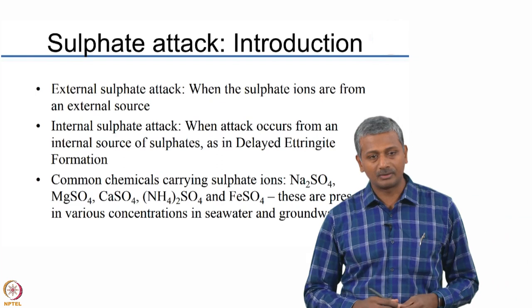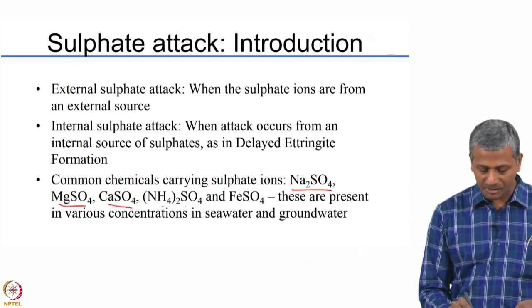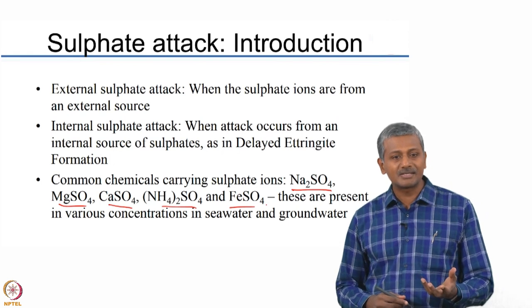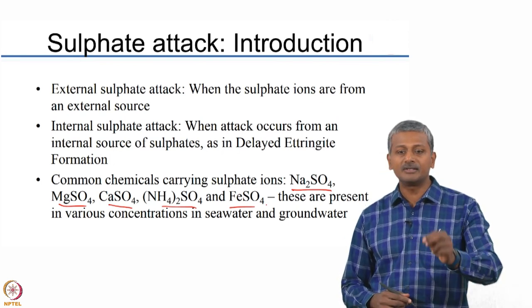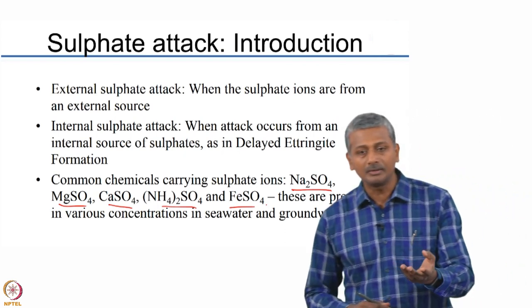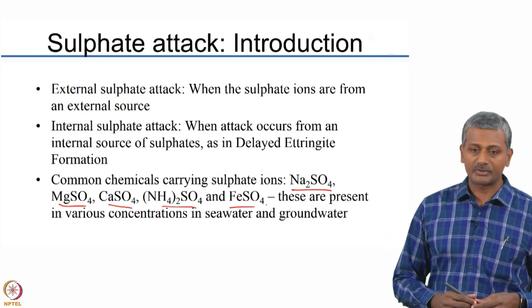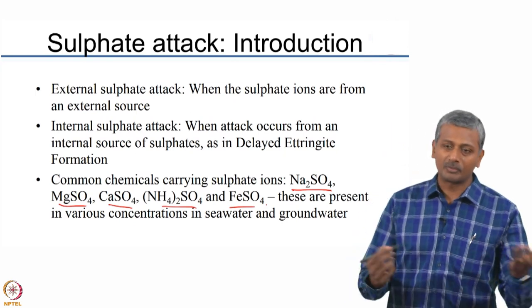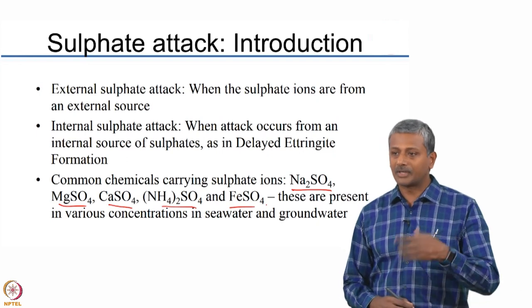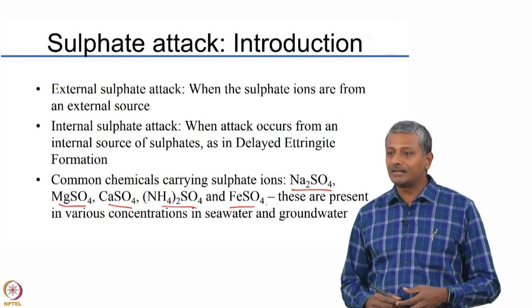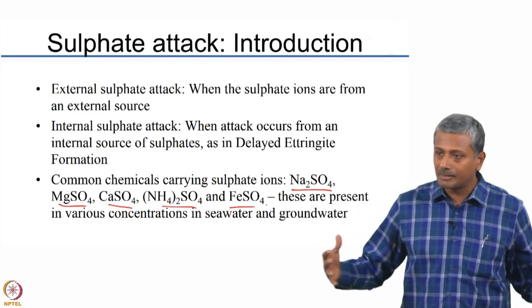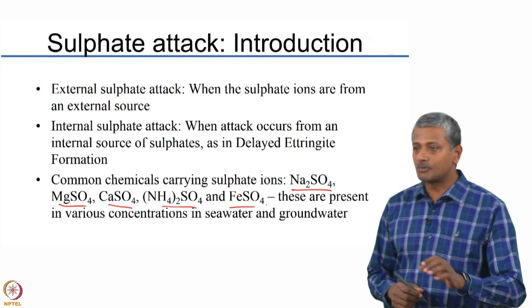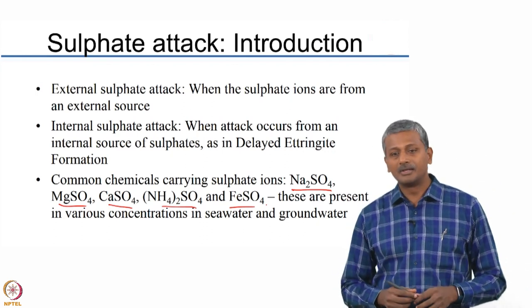There may be variations in the types of sulphates actually attacking the concrete — for example, sodium sulphate, magnesium, calcium, ammonium, or iron sulphate. You need to understand which species is present in the local environment because that dictates solubility, which in turn dictates how much will actually get into the concrete. Solid sulphate in the external environment has no way of entering apart from minor mechanisms; in reality, ground water dissolves sulphates and carries them into the concrete through its porous structure. The amount of dissolved sulphates is very important to consider.